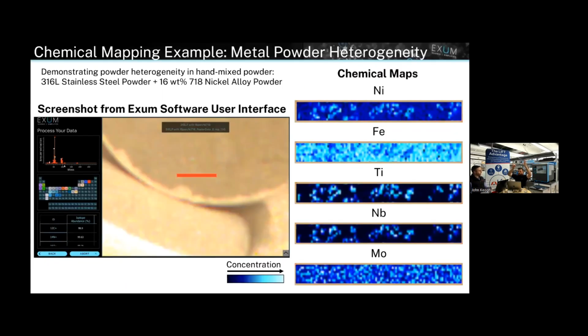And to that point, let's say you did a raster map and you saw you had this big old spot, like we saw in those core samples for the NIST earlier, or like what Ellen just brought up here on the screen, right? This is actually a mixture in here. And we can actually see that it's not perfectly mixed, right? If we look at where the iron is, maybe a darker blue, that's actually a lot of titanium and niobium. So in this mixing, maybe that's an acceptable amount of nickel and iron mixing with the titanium and niobium. Maybe it's not. Right? But also, if you get a really, really hot spot in there, you can go back exactly where you analyzed on that map, put a spot, and just dwell into that single particle. Yeah. Drill down.